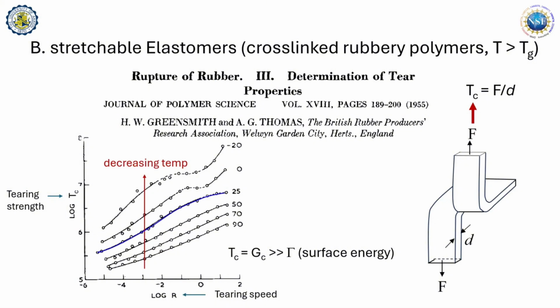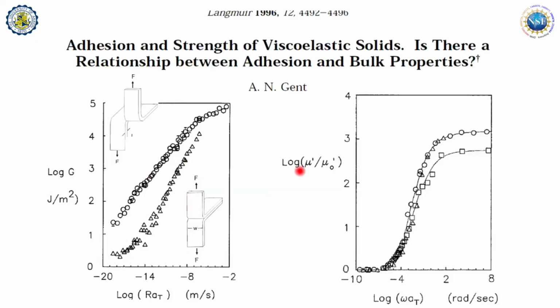So for example, if this is done at 25 degrees, at a higher temperature, the resistance is much lower. But can't I just realize that higher temperature is equivalent to stretching slower? So you can do a shift. Look at this shift. You can just do a shift and claim that everything can be understood by the fact that your polymer relaxation depends on temperature. So indeed, over this region, the more complicated things later, over this region, you can think about superimposing it using WLF shift.